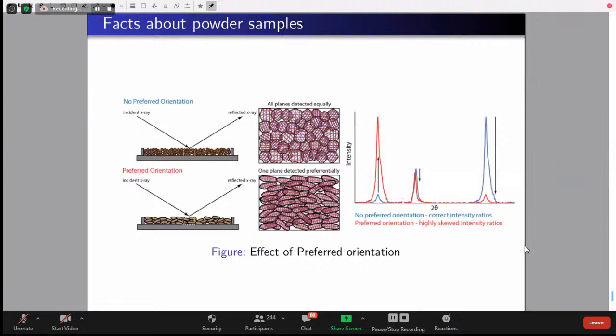Then to calculate the average, we have to plot for all the families, all the peaks? No, ma'am. Family of peaks. You can't do that, because if you separate the analysis for each and every peak, that particular value itself is the average crystallite size. From this plot, sir? You mean the Williamson-Hall plot? Yes. From the intercept, Williamson-Hall will give the average crystallite size. Yes, that is the average crystallite size only for that family of planes. Okay, sir. Thank you, sir.